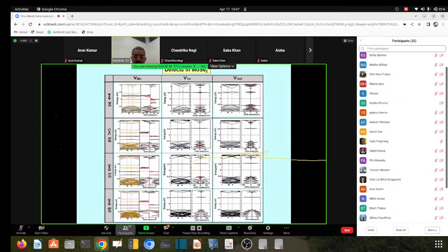If you create vacancies, here the first column is a vacancy of molybdenum, the second column a vacancy of selenium, and the third column a vacancy of selenium pair. Also for MoS2, all vacancies are paramagnetic. Only in one case, MoSe2 with a vacancy of molybdenum, is there magnetism, because the spin up and spin down density of states differ. I'm showing both bands and density of states here. In the left column, that I'm pointing at, the results are shown for 4x4, 5x5, 6x6, and 7x7, the same thing, but we put 8x8 to reduce a little bit the size of the view graph.